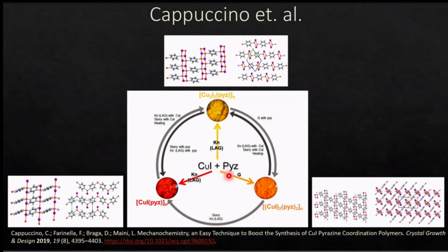But they were also able to use dry grinding in order to make this orange polymorph that we recognized in our work, but we couldn't find any reports of an orange polymorph in any other papers. So this was actually the first paper to report this orange polymorph, and this allowed us to understand these relationships and what we were seeing.